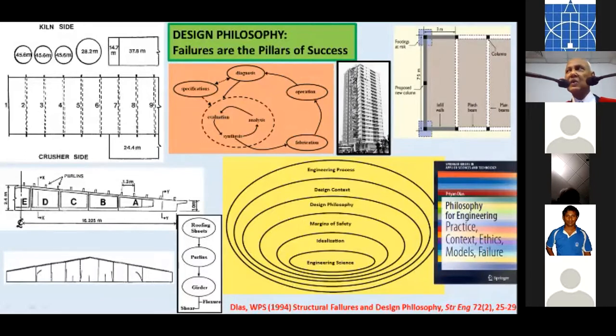So that was a method of construction that was popularized by Dr. Kulasinghe, because you can post-tension it all down at ground level and lift it up to this very high elevation. So then these structures, of course, so two of these girders, there were purlins in between them, and there were roofing sheets on top of these purlins. So the reason this collapsed was because about 150 millimeters of cement dust had accumulated on the roof, because the kiln precipitator of the cement factory was malfunctioning, right? So cement dust was spread not only on this roof, but all over the countryside when we went to inspect it, right? So, of course, that is why it collapsed.